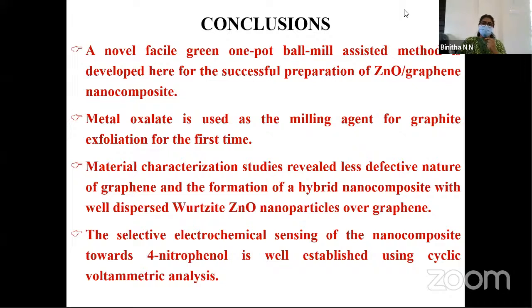So in conclusion, here a novel facile green one-pot ball mill assisted method is developed for the successful preparation of zinc oxide graphene nanocomposite. Here for the first time, a metal oxalate is used as the milling agent for graphite exfoliation. The material characterization studies reveal the less defective nature of graphene and the formation of a hybrid nanocomposite of well-dispersed zinc oxide nanoparticles over graphene. The selective electrochemical sensing of the nanocomposite towards 4-nitrophenol is well established using cyclic voltammetric analysis.